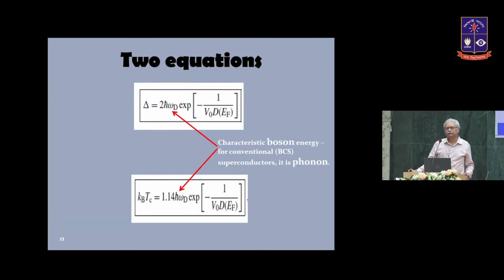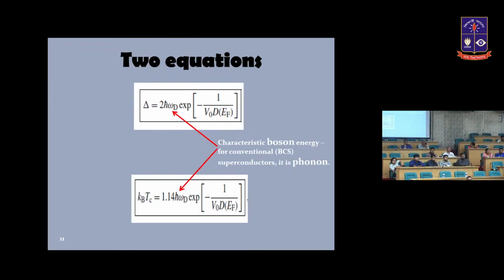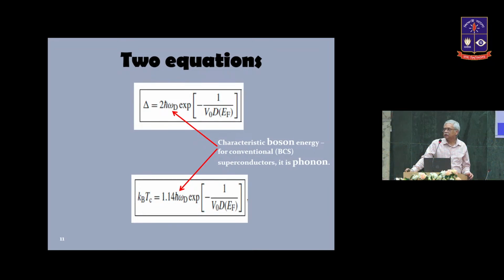Okay, so there are two very basic equations. These equations are also kind of fundamental, except for minor modifications. All superconductors show a gap structure, and in BCS superconductors, the superconducting transition temperature actually depends only on two special parameters. One is the characteristic energy of the phonons. We call it Debye temperature. And the term you see in the exponent altogether, this gives you the electron phonon coupling constant.